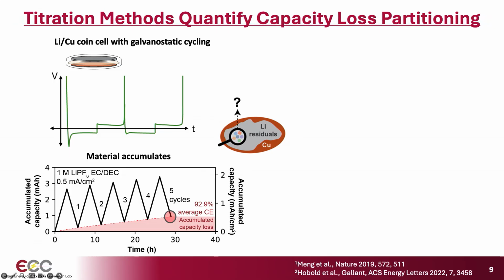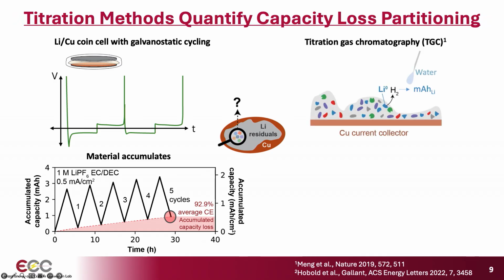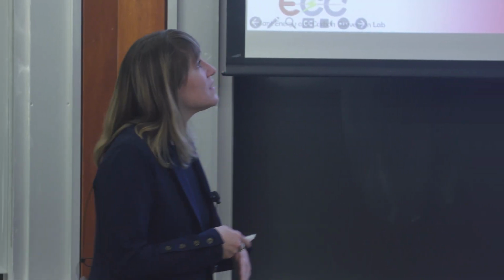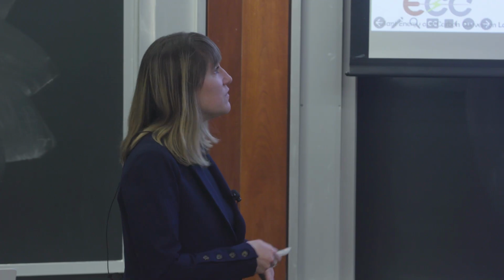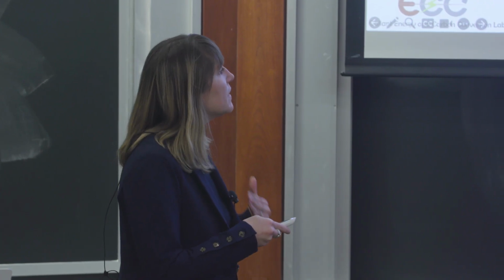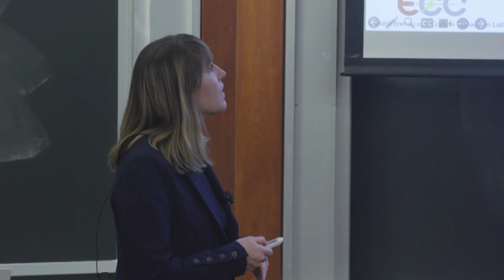So it turns out that we can actually exploit the fact that there's material accumulating on the current collector during cycling. For instance, as I mentioned, the material contains metallic lithium. So one thing we can do is react it with water, and the lithium will evolve hydrogen stoichiometrically. We can count up how many moles of hydrogen are evolved, and then convert that to the equivalent capacity that was on the sample that corresponds to that capacity loss mode. Okay, so we can figure out how much is there. This is work done not by us, but by Shirley Meng a few years ago.